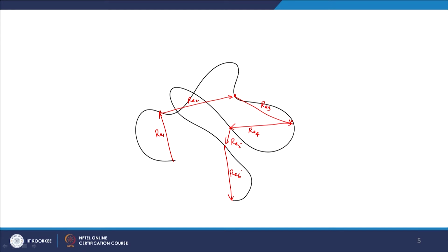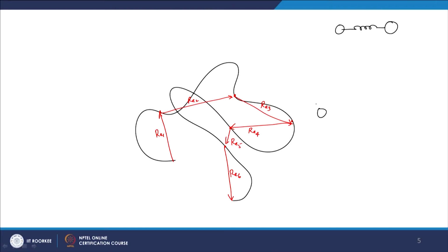And the advantage of doing this is, unlike the first case where I represent the polymer chain by simply one spring, we now have some sort of internal flexibility inside the polymer chain. So, if I now replace this with something like this, what I have is actually a collection of springs. Each of them will have a spring constant k, but each of them will have different extensions. Okay.